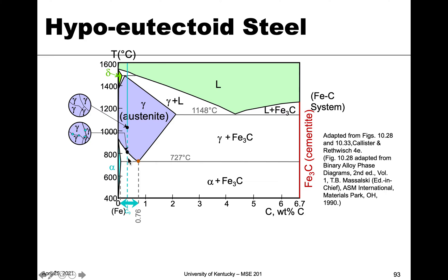And if we continue to decrease the temperature, we'll get more and more alpha in this amount. And so here we see that we form alpha regions. Here it's not in the typical spherical shape. It's along the grain boundaries, but it's still the same idea. We have more and more alpha the further we decrease in temperature to the point where we're right above this eutectoid, which is 727.